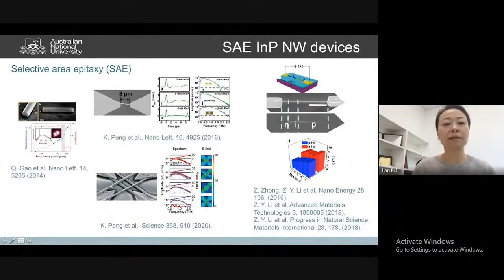So over the past, we have demonstrated single nanowire based lasers. You can see the lasing from this single wire. We have also demonstrated broadband terahertz response from single nanowire detectors. And later on, we fabricated a crossed nanowire based terahertz detector. Using 4 crossed nanowires basically enhances the signal. With these crossed nanowire networks, we are able to measure the polarization state of the incident terahertz radiation, because you can use this to form a polarization sensitive channel. So this is the interesting work coming from single indium phosphide nanowires.